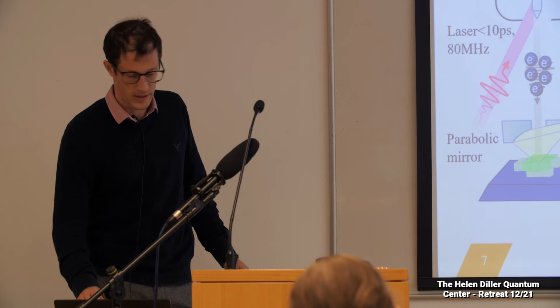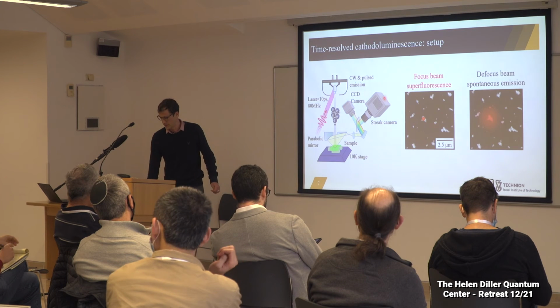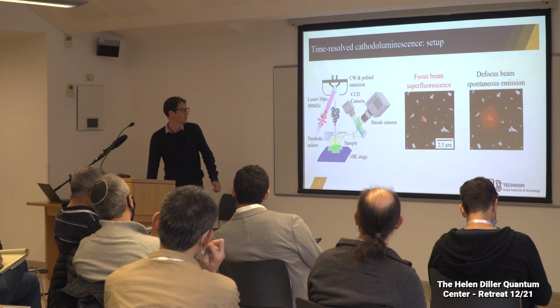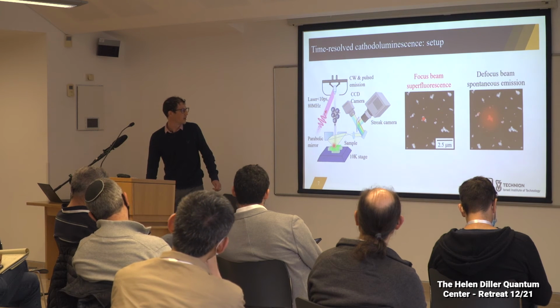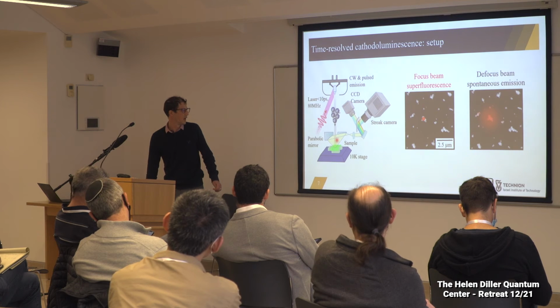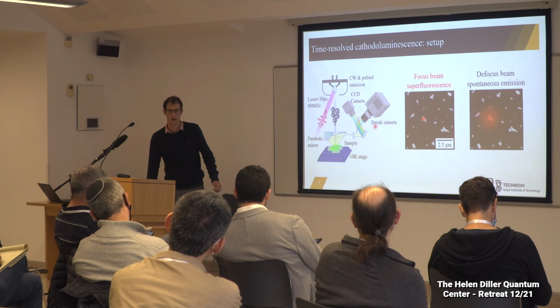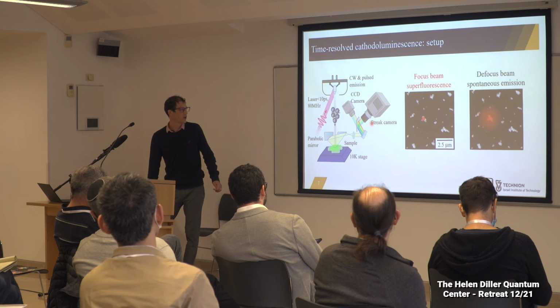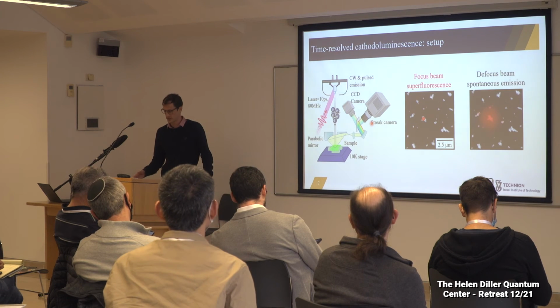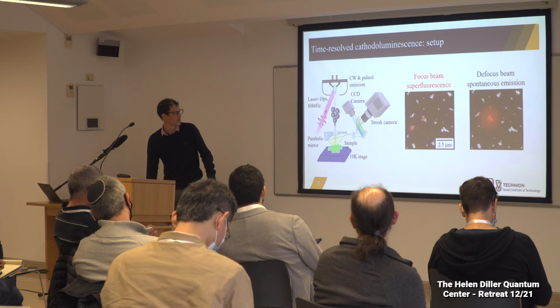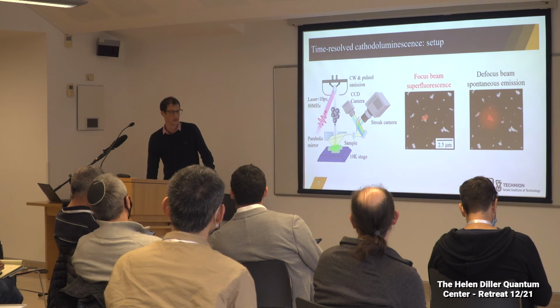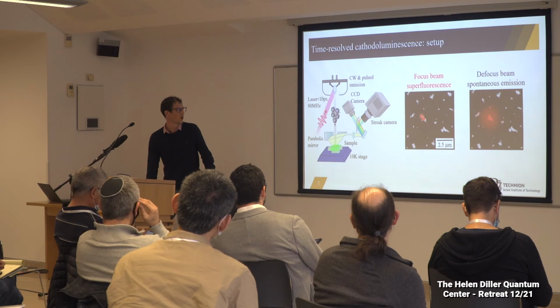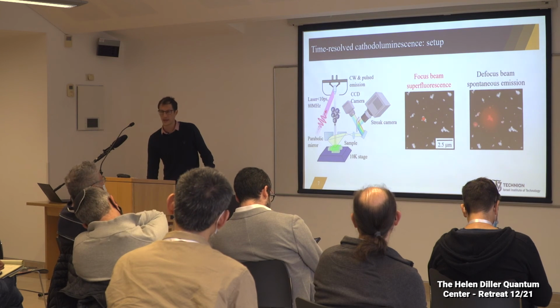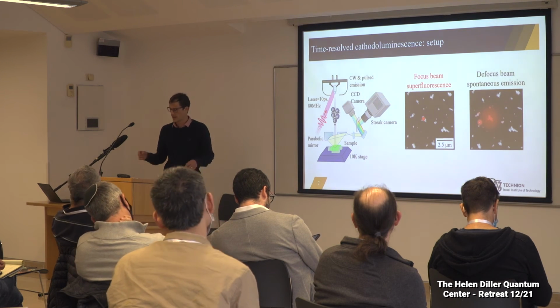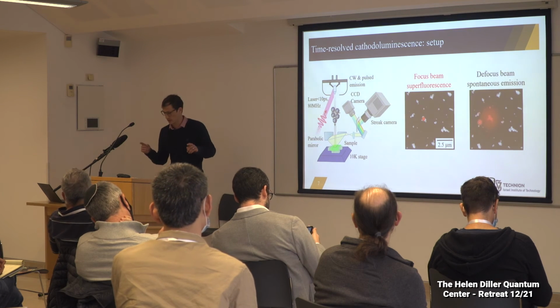So how do we test it? We have a time-resolved cathodoluminescence setup. The electron gun is triggered by a pulsed laser, which results in an electron pulse that hits our sample, and we collect and analyze the light that comes out of the sample. We made two realizations of this experiment. In one, the electron beam is focused to a size smaller than a superlattice so that it hits a few quantum dots, and the other is a defocused electron beam, where the electrons of the pulse are very far from each other.